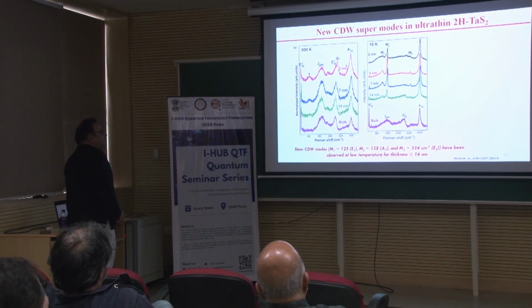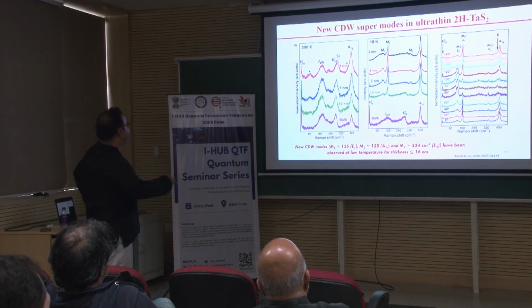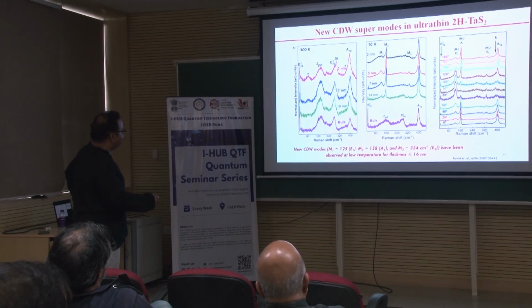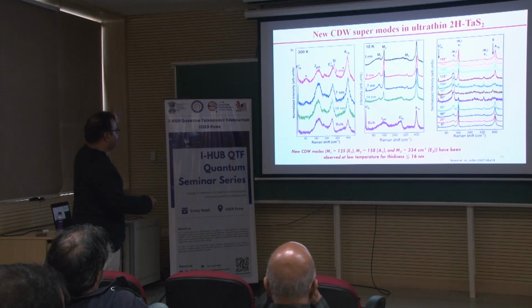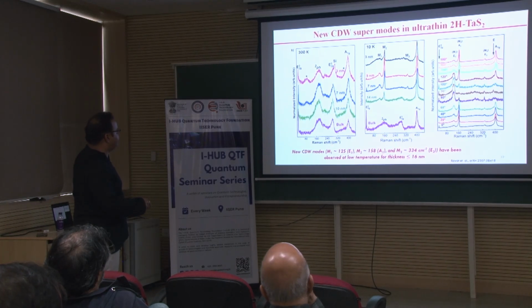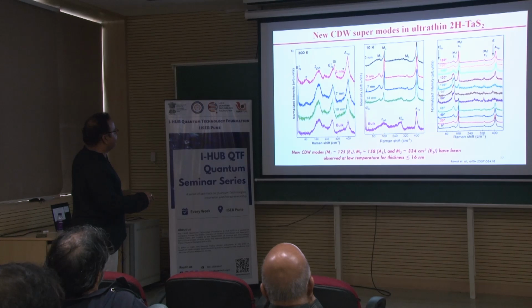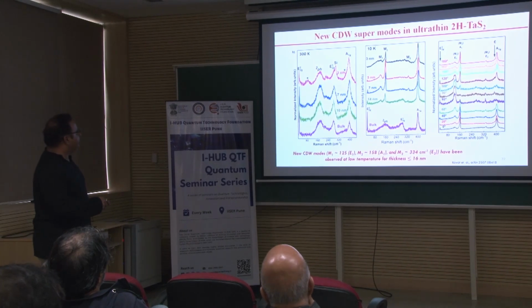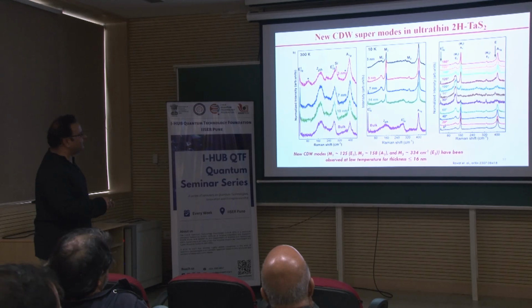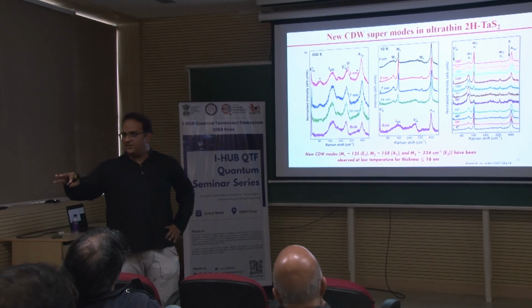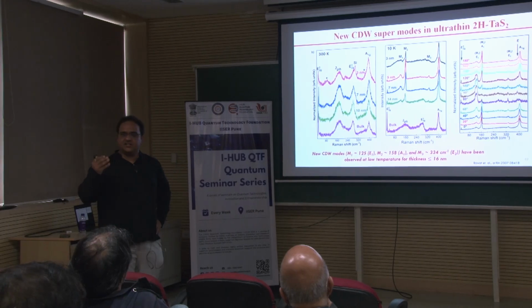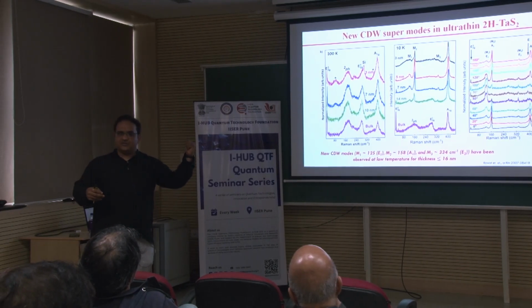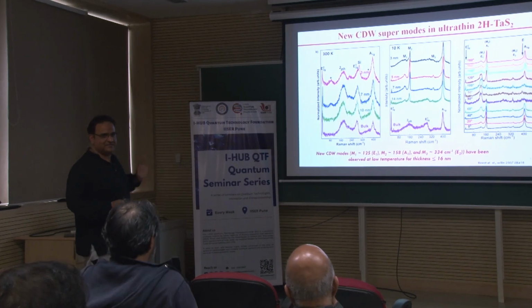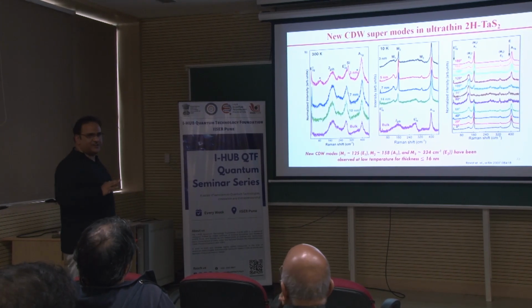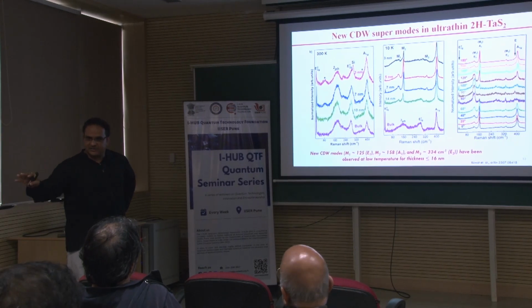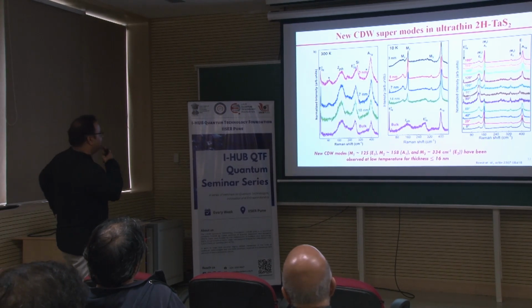Let us see the Raman, how it looks. Okay. So, this is 300 Kelvin, this is bulk, the very usual Raman spectra we have seen in the previous story of the 2 phonon mode, 10 nanometer, 7 nanometer, 3 nanometer. Now, in 3 nanometer we have a contribution which is coming from the substrate because it is an extremely thin layer. If I go beyond 3 nanometer I will have higher substrate contribution, and I will not be able to resolve or fit my Raman data. So, that is my limitation. So, we stick to the 3 nanometer, and it is a centrosymmetric bilayer system and it is a unit cell, alright.